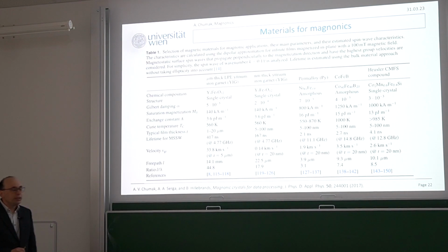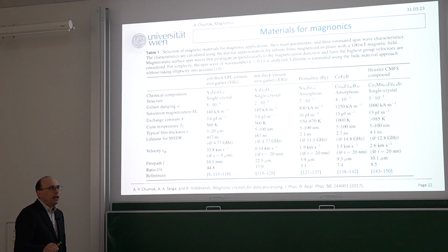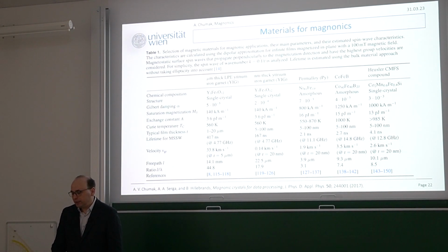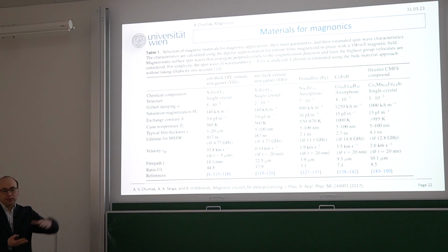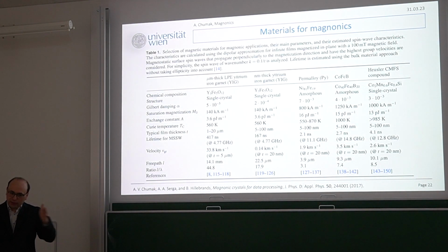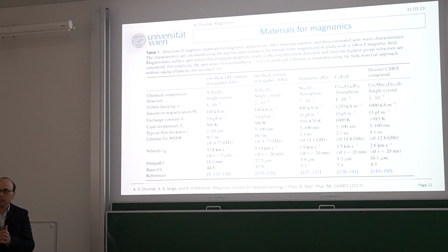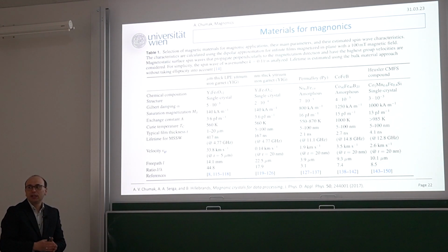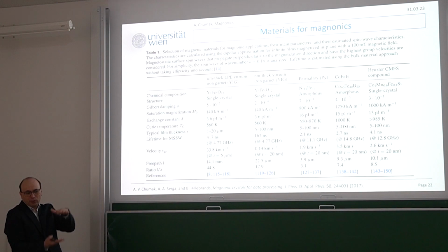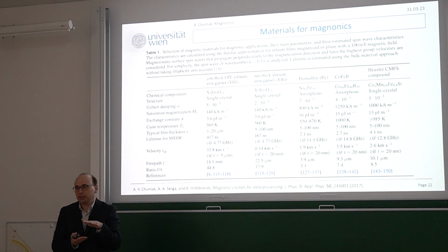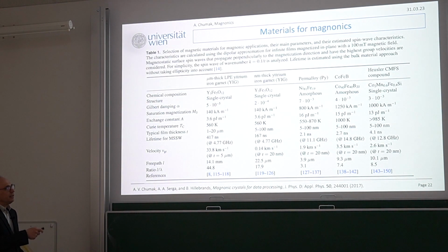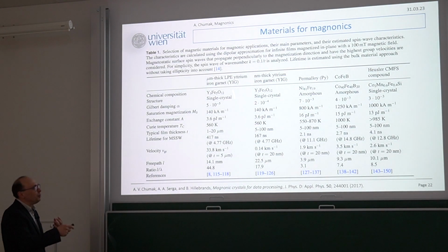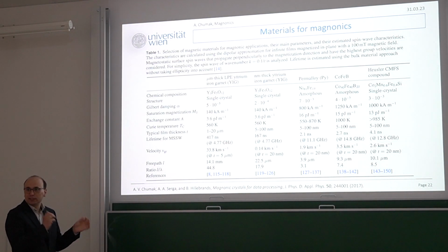The reason is the following. One of the main advantages of magnonics in terms of processing data is scalability. We can go to very small wavelengths and very small sizes. But if you have a sample 5 microns thick, you cannot reach 50 nanometers. There is no technology for that, or there would be some huge pillar. Therefore, if you want 50 nanometers, we also went down to thicknesses of 30, 40 nanometers, and it's possible. Simply scalability, but then ideally we would do quantum magnonics with this property on this scale, and it's kind of win-win.